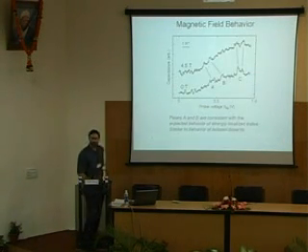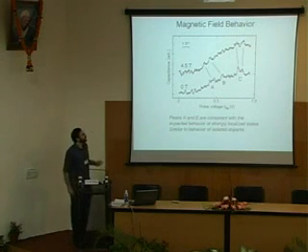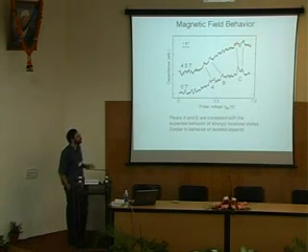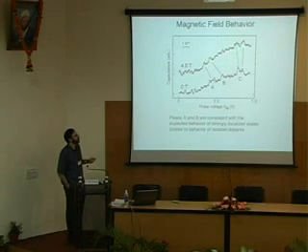All right, I'll just show one more data plot. This is the behavior in a magnetic field. This is just one data set instead of 3, so the signal-to-noise ratio isn't quite so good. There's peaks A, B, and C. As we put on a magnetic field, on average, we see peaks A and B end up going to lower energy. Peak C ends up splitting. This makes us very happy because we were supposing it was 2 different electron peaks in the first place, and this makes that on more firm footing.